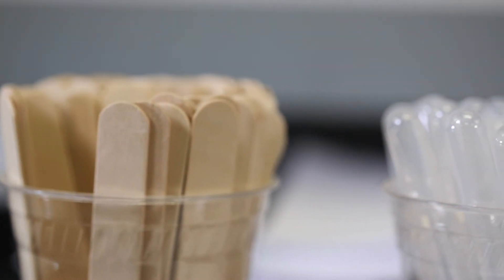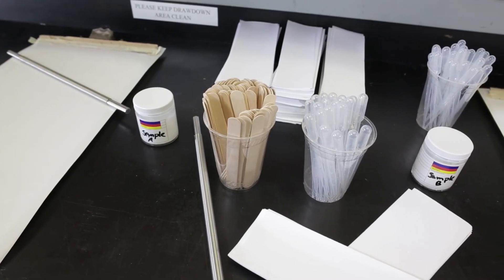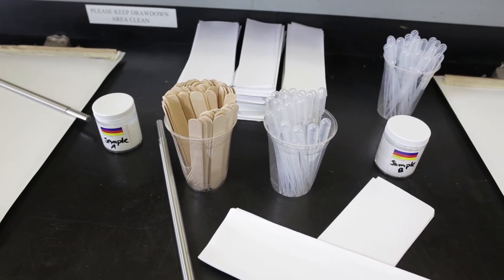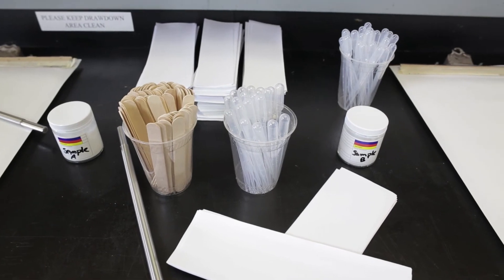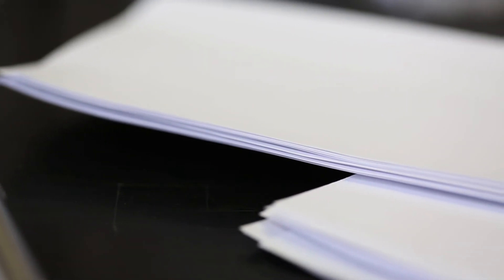Adequate testing is integral to successful product development. We create drawdowns with our adhesive, to test the adhesive's label application properties. Creating a drawdown ensures the product is adequately wetting out the liner. It also illustrates how well the adhesive transfer coats when applied to the substrate.